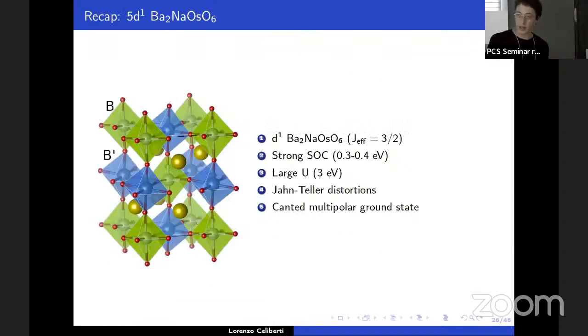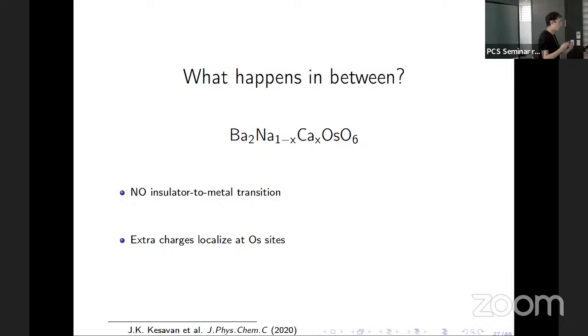So this is a recap of what you have seen so far: strong spin-orbit coupling, strong electronic correlation, Jahn-Teller distortion, and canted magnetism in this barium sodium osmate. Now we're interested in the doping of this material. What has been done is to change sodium atoms to calcium. This basically introduces electrons in the system, which have been shown to localize around the osmium site. There's this charge transfer from the calcium to the osmium, and different concentrations have been measured. In particular, at no concentration do you see any insulator to metal transition. It stays insulating from zero calcium to full calcium.